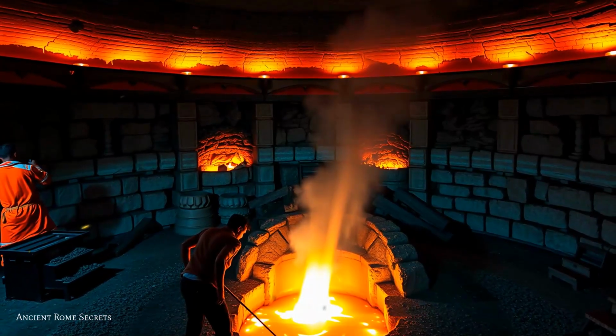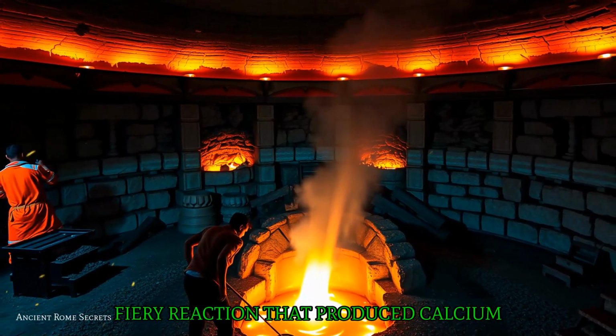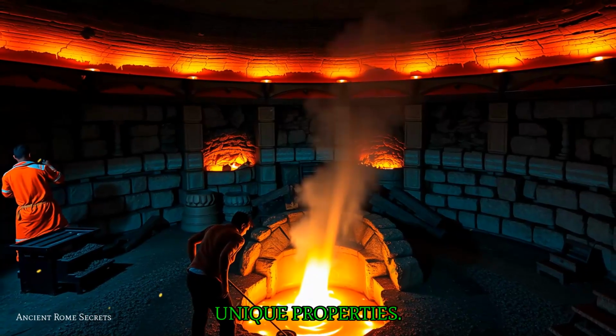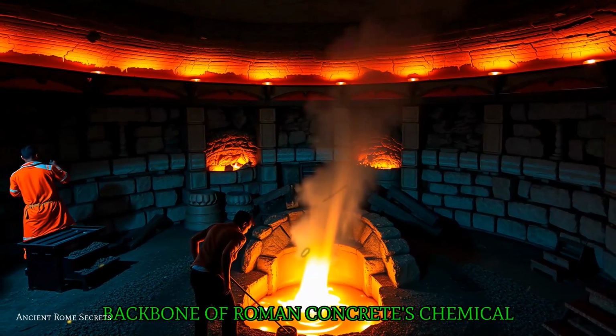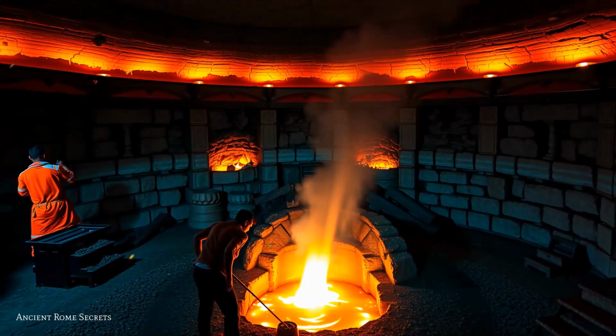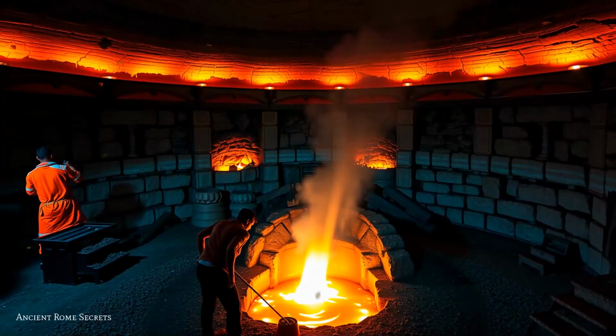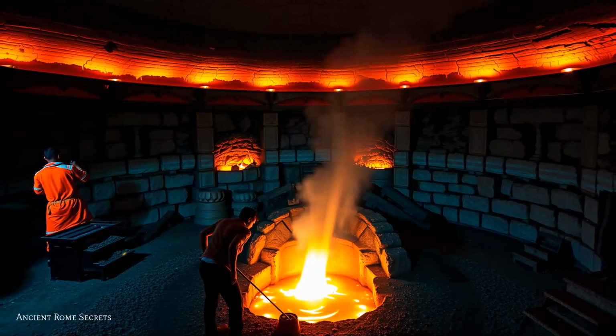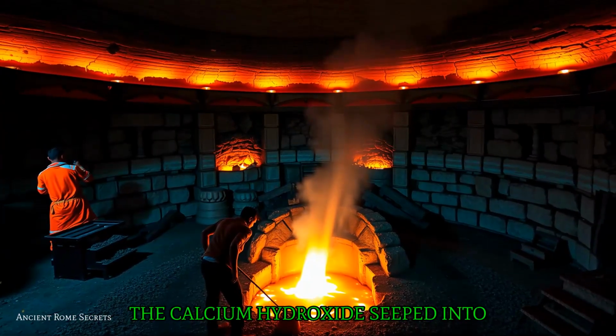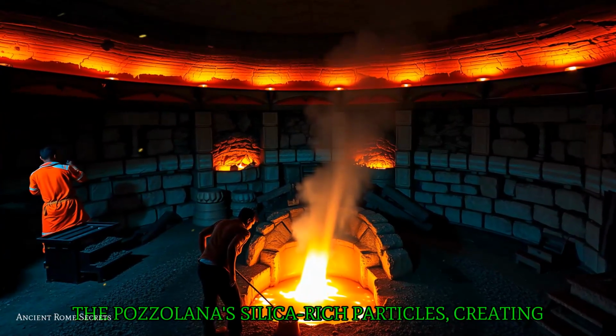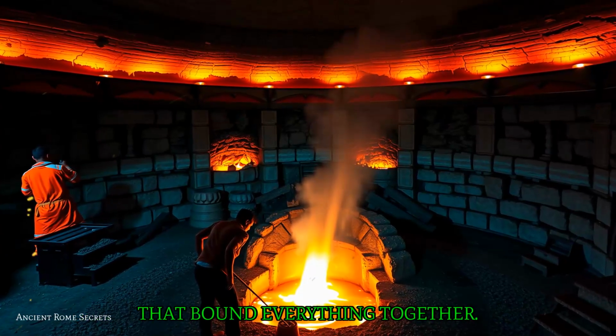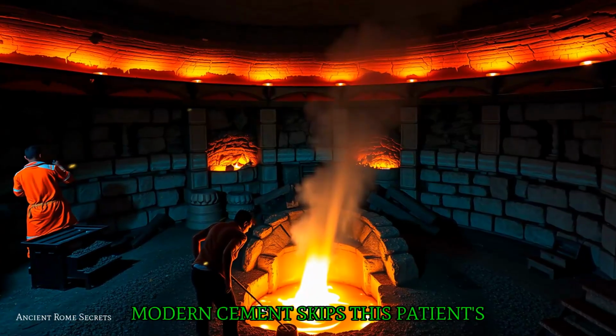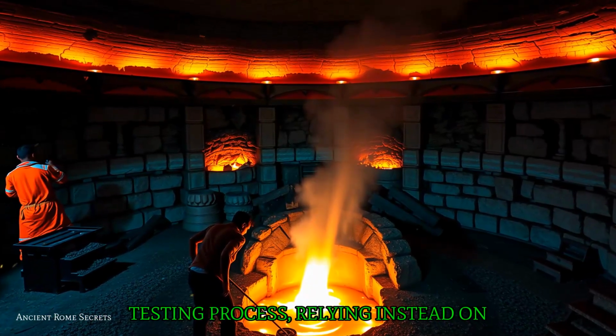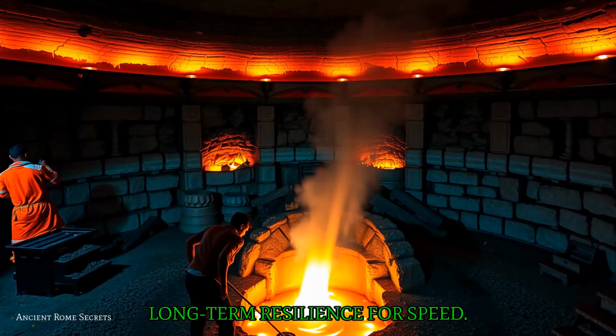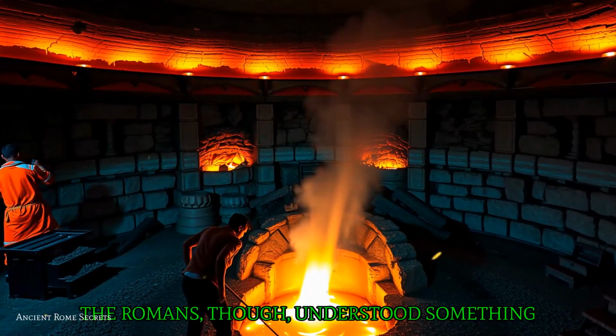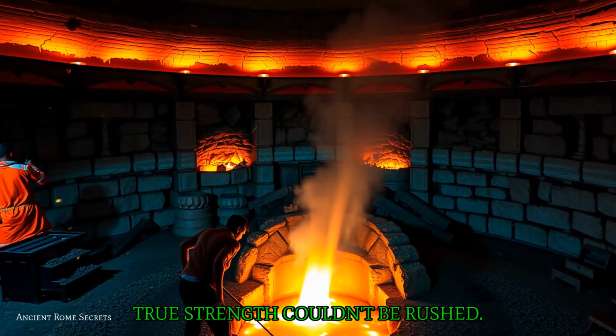So they slaked it, carefully adding water to trigger a fiery reaction that produced calcium hydroxide, a stable paste with unique properties. This slaked lime became the backbone of Roman concrete's chemical magic. When mixed with volcanic ash and water, it didn't just harden, it initiated a slow, transformative reaction. Over months or even years, the calcium hydroxide seeped into the Pozzolana's silica-rich particles, creating interlocking crystals and gel-like structures that bound everything together. Modern cement skips this patient process, relying instead on rapid-setting compounds that sacrifice long-term resilience for speed. The Romans, though, understood something profound. True strength couldn't be rushed.